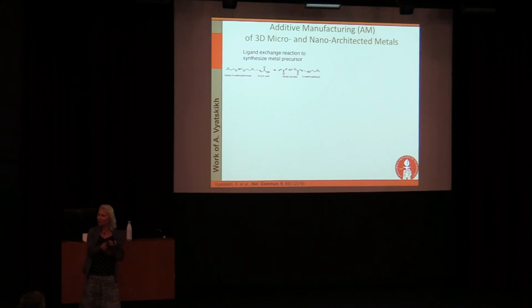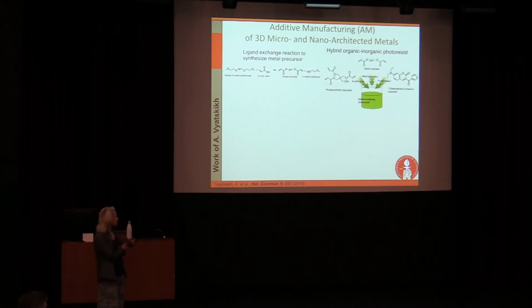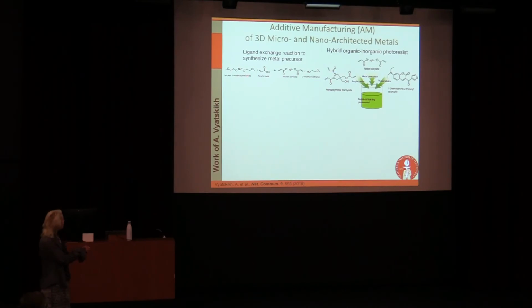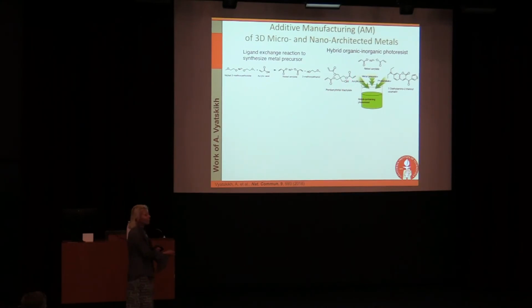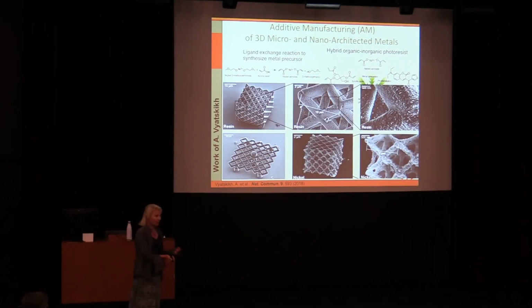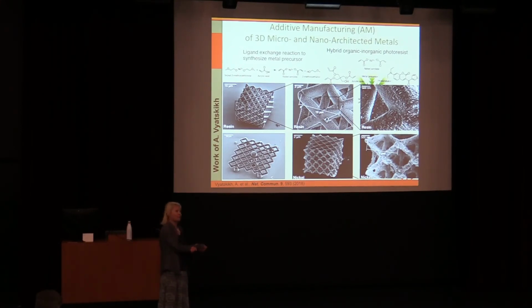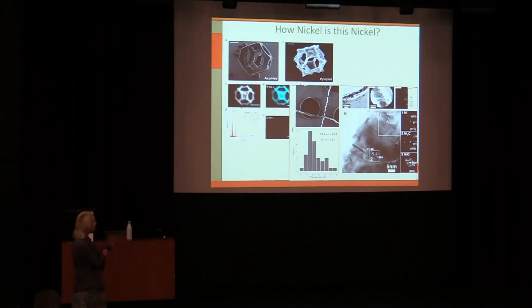So additive manufacturing. Are people interested in additive manufacturing here? Seems like this would be functional material. What we've discovered is that you can actually track various ions in the resin. For example, this is some kind of a moth effect. We trap a nickel ion in this organic shell, and you can then undergo a ligand exchange reaction. And so you can create an acrylic-based resist to start creating these architectures out of metals, so that we're not only limited to polymers. What my student Andre was able to show is that you can make a nickel-containing resin and then pyrolyze it, which is a fancy word for burning. And when you burn off all the organics, you end up with an additively manufactured nickel material. You can see the unit cell size here is only 2 microns, and each individual beam is less than 500 nanometers. And that's not something that additive manufacturing people have accomplished to this point.